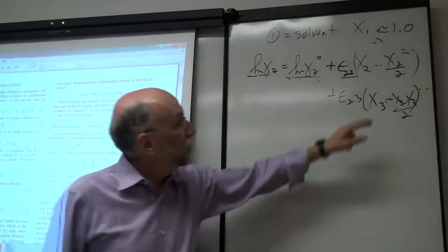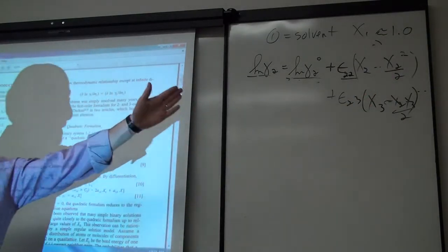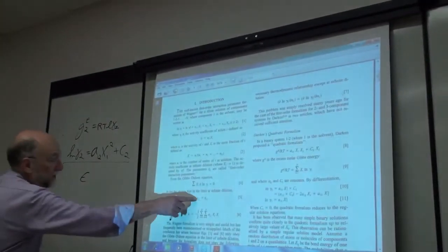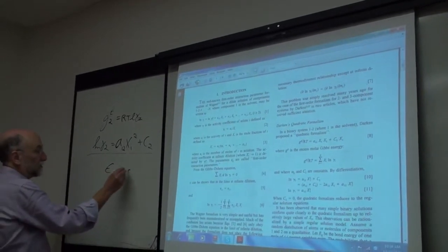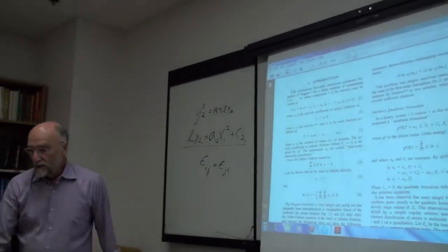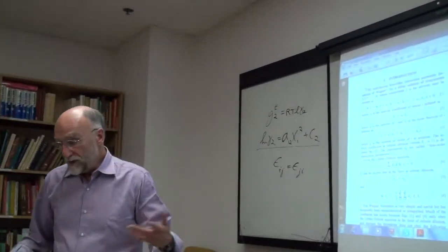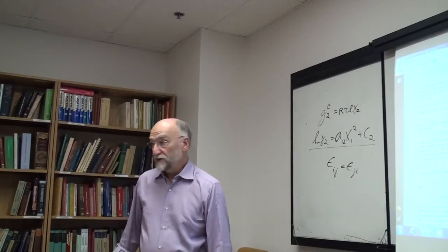But in the FactSage database, the correction terms have been applied. So the FactSage database is not Wagner's formalism, it's the unified formalism with the proper term in here. And again, the cross terms are equal, just as it is here. Epsilon ij has to equal epsilon ji when you do the entries. So the formalism in the FactSage database is the modified Wagner formalism with the correction terms in.